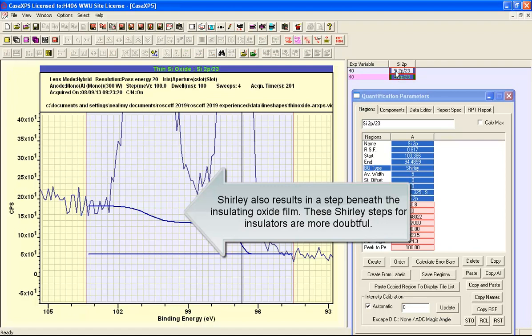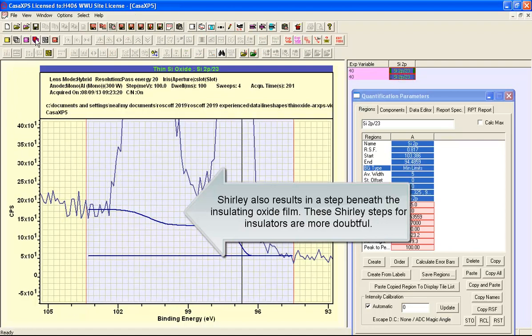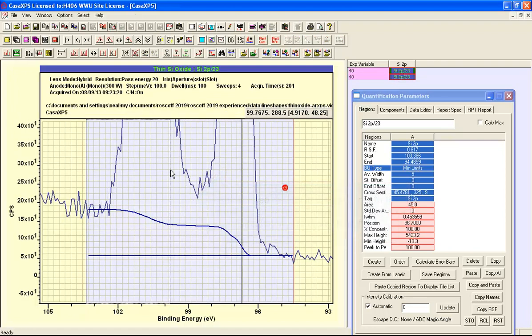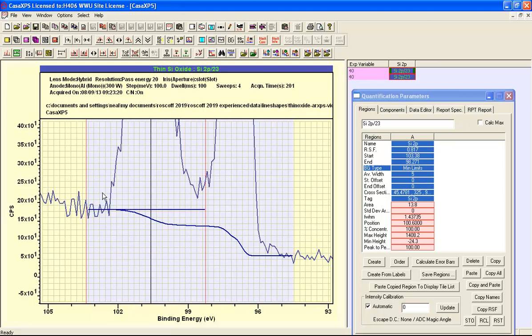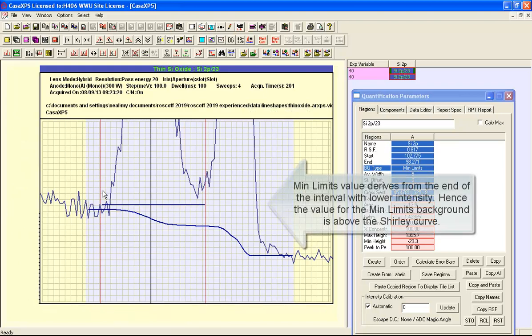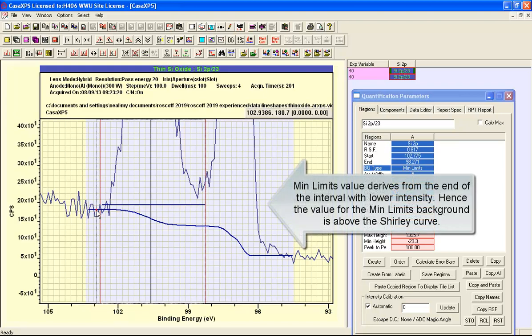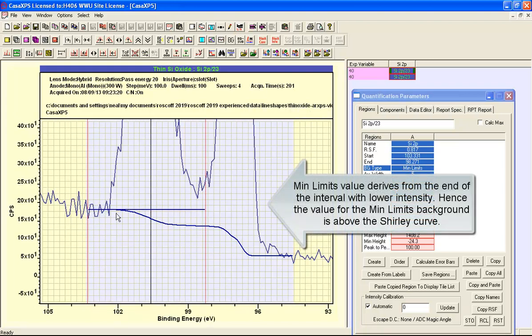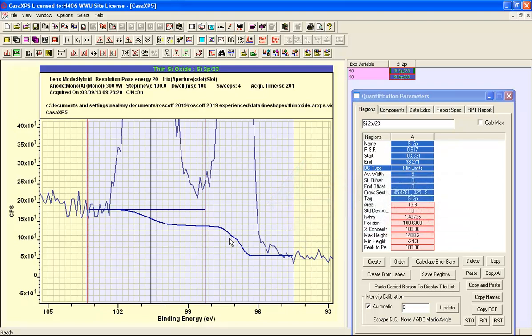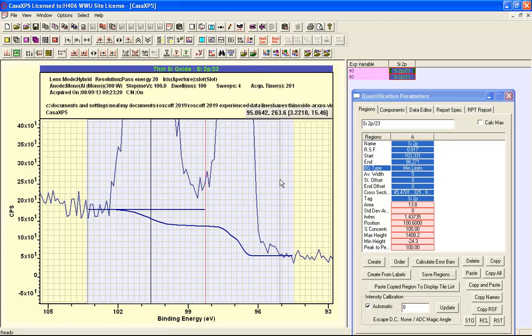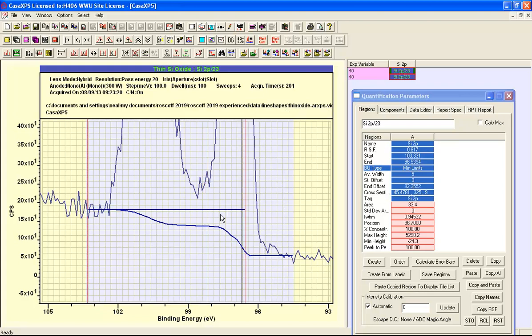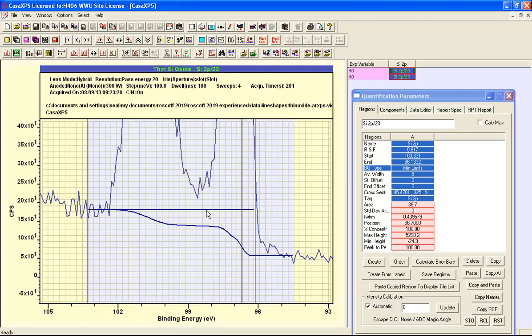If I reverse these you can see that this is the type of flat background that we would expect here, and we need the Shirley background to rise up and perhaps join this somewhere around here. So there's clearly a problem if we either choose a Shirley background to represent these or attempt to use a flat background beneath both of these peaks. Neither of these will work particularly well and we would really like to have a combination of both.